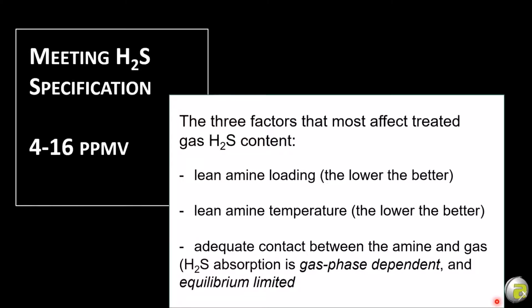We want that lean amine loading, or how much residual H2S is left in that lean solution, to be as low as possible for the solvent that we're using. So that means the regeneration is important. We have to drive the H2S out of that amine solution properly inside the regenerator column. And on the other one, the lean amine temperature, the lower the better. The cooler amine has a higher capacity to absorb acid gas, so that's a big benefit in meeting spec. And the secondary knock-on benefit is that the cooler that amine temperature is, the cooler the treated gas temperature tends to be, and that means that for any downstream dehydration, the cooler gas holds less water, so you're not putting such a large load on your downstream dehydration equipment.